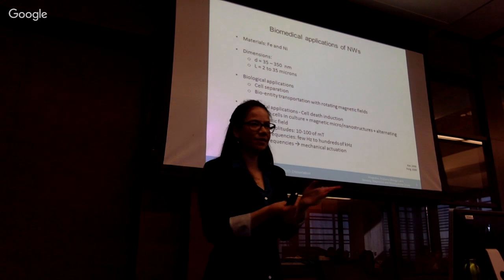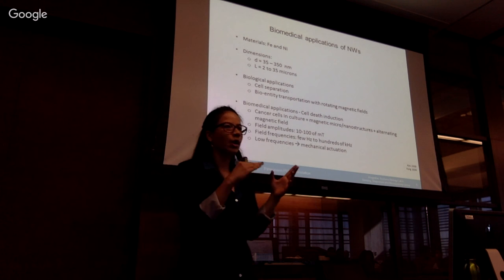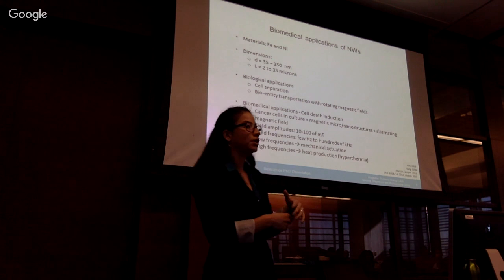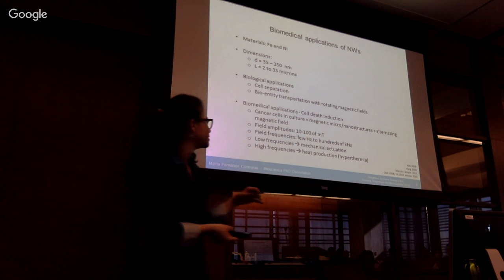The amplitudes they use are from 10 to 100 millitesla, and the frequencies do cover a broad range. They can go from a few hertz up to hundreds of kilohertz. If you use low frequencies, the principle I just described before, this nano compass needle principle, holds true. So you do have a mechanical actuation because the wires do oscillate. However, if you go higher in the frequencies, this is no longer possible. The wires cannot follow the field, and you have a heat production associated to it. And this is basically the principle of what they call hyperthermic treatments.